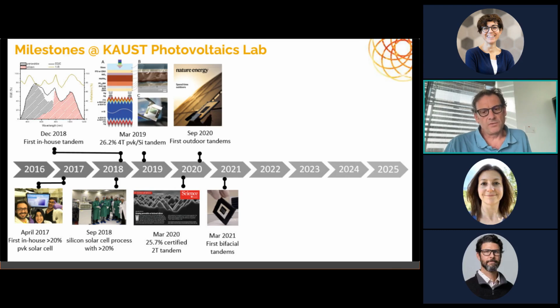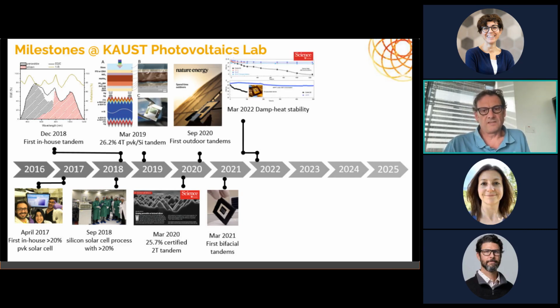One interesting approach, and also what you see specifically for large-scale PV deployment, is bifaciality for silicon. And we also explored this idea for tandems. And actually, it is definitely a valid idea. The interesting thing about a perovskite-silicon tandem is that you can use a quite narrow bandgap perovskite, which means you don't have to add bromide. So you could end up with a quite stable composition and have a good device.